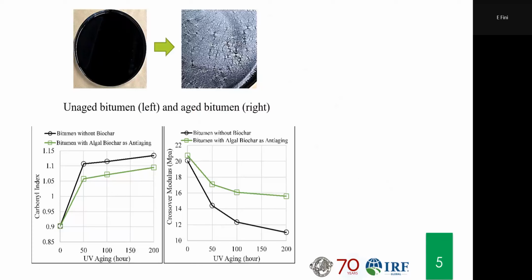But regardless, if you have anti-aging or you don't, you cannot reduce it to zero. Almost no material does not age at all. You can slow it down, you can reduce the rate of aging, but as you can see here, the one in green, which has anti-aging, also ages. The difference is it ages slower and it stops at a much higher modulus. You can see, like at 16, the other one keeps going down. So the rate is reduced, but you cannot bring it to zero. None of the anti-aging I have ever worked with makes it go to completely no aging. So it is anti-aging, but really it means it's slowing down the aging.